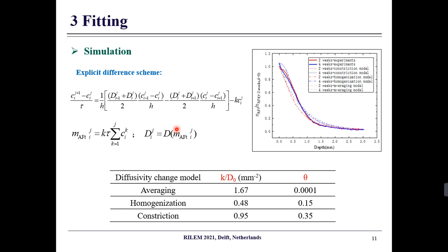By fitting two unknown parameters, the reaction kinetic coefficient of the crystallization reaction and the reduction parameter of the liquid film, the experimental ettringite amounts are simulated by the proposed diffusion reaction model. Just like this top right figure shows, the difference of ettringite between 2 weeks and 4 weeks is very small. The fitting parameters are given in this table.